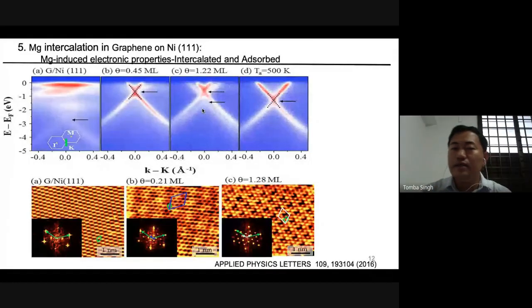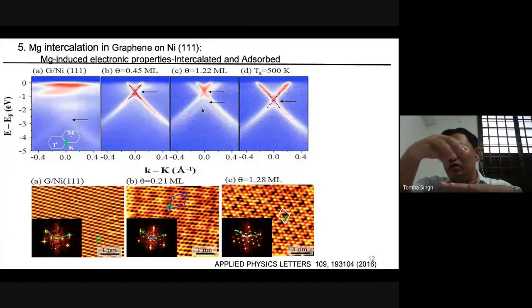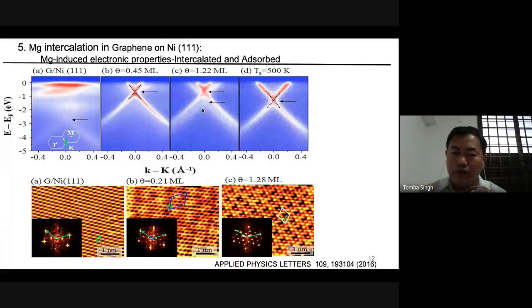If we heat it, then most of the adsorbed magnesium goes below the graphene as an intercalated state and the crystal quality improves. That's why we got a proper Dirac cone here. So the different locations of the magnesium can be identified using STM surface topography. These bottom images are STM topography at different coverage. The first one is before magnesium adsorption or intercalation. The inset image in the corner is the FFT, fast Fourier transform, image of this image.